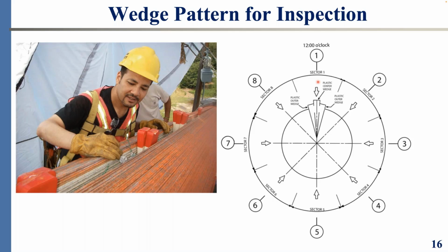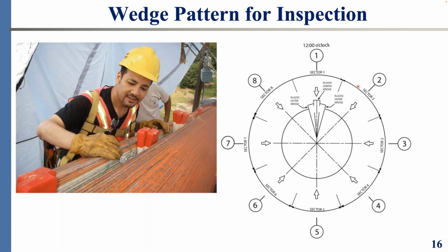What I mean is, you look at wedge 1, you see the wires only along the 2 sides of the wedge. That's it. So if you go to wedge 2, which is right there, or up until wedge 8, you don't see any wire in between the 2 wedges. You see wires only along wedge 1, along wedge 2, and so on. So speaking of that, you can see here actually that here is wedge 1. You see the wires along this way, along this particular wedge. When you go to wedge 2, you see the wires along that particular wedge, but anything in between you don't see.